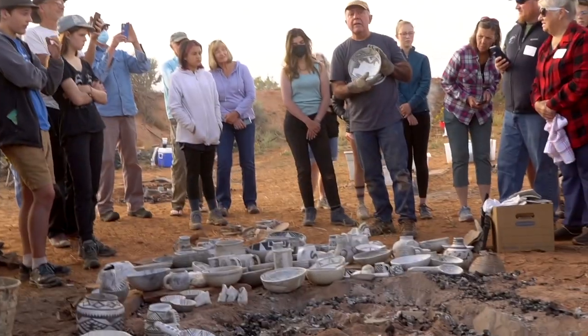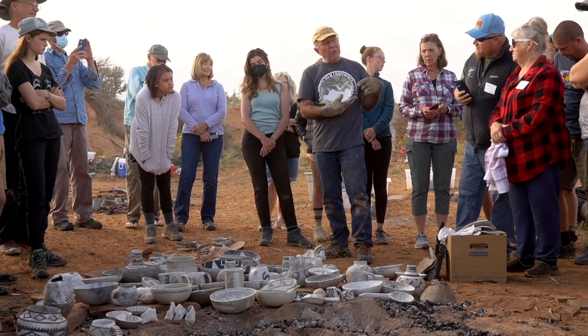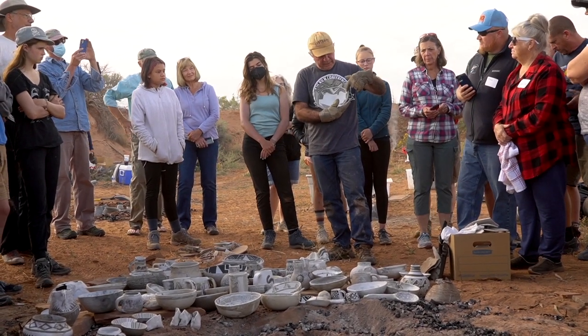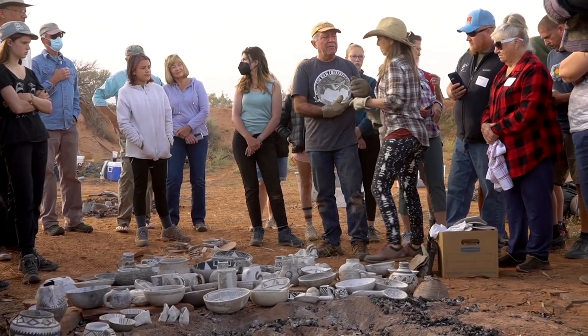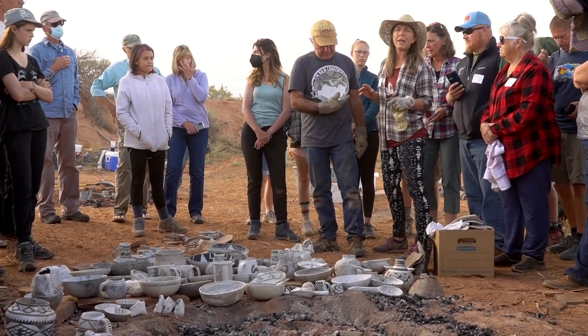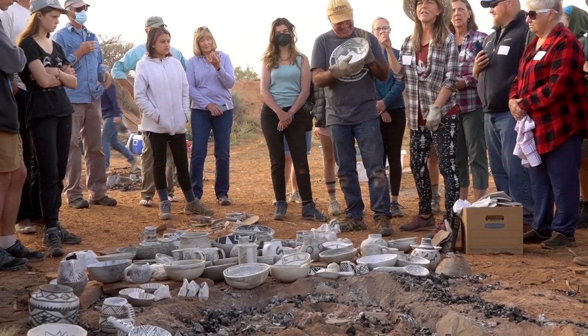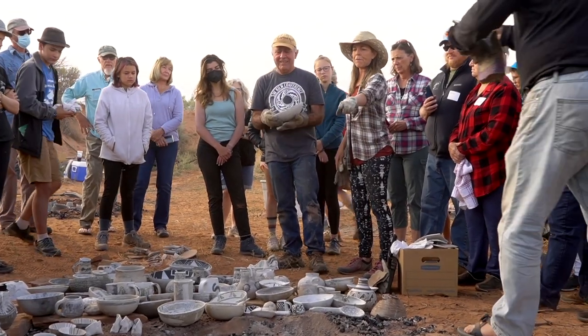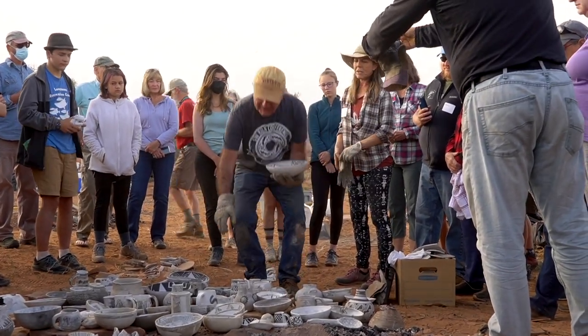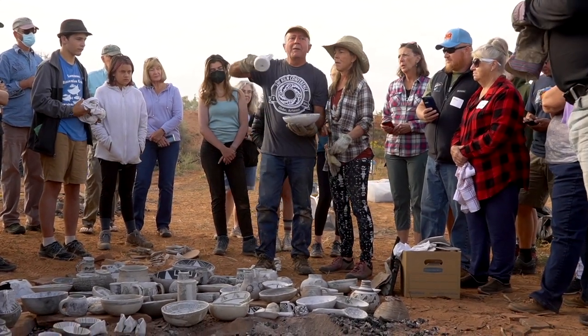So again, pretty good color, but the paint, I don't know why it does this, sometimes it gets this kind of filmy look over the top of it. So that's too heavy of an application. Have you seen this man paint? I mean, his paint's that thick. It'd be great, in that first kiln we did the other night, when we want a heavier ash coverage. But just for the record, this had the same application.